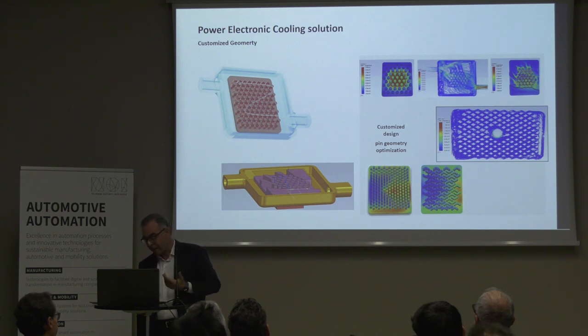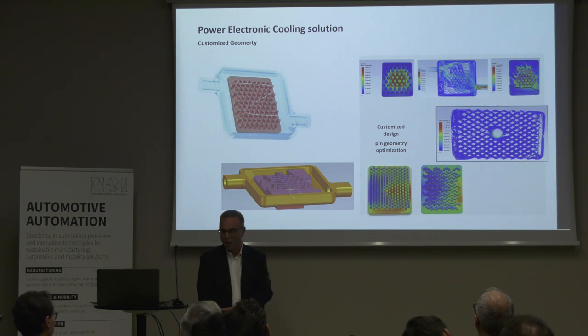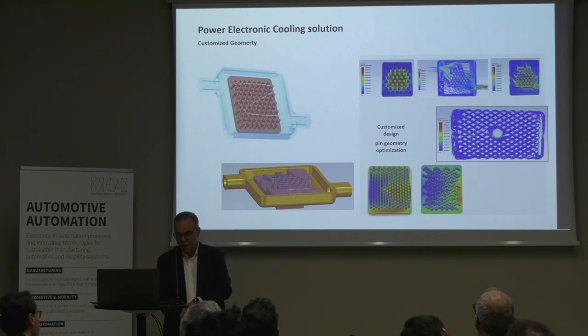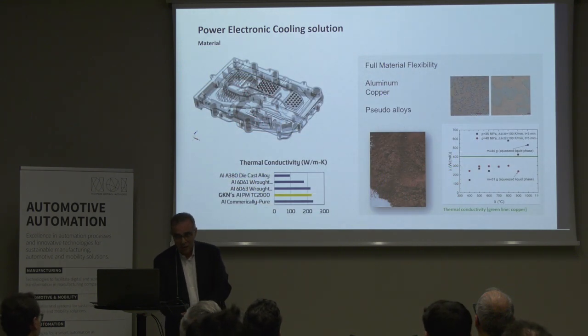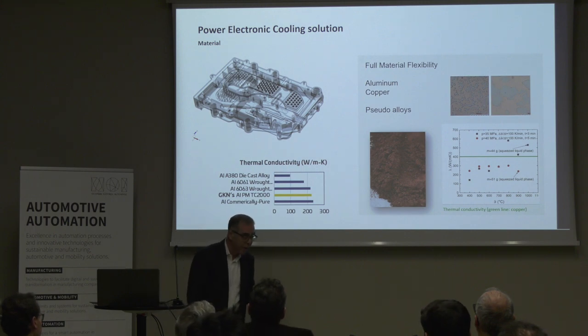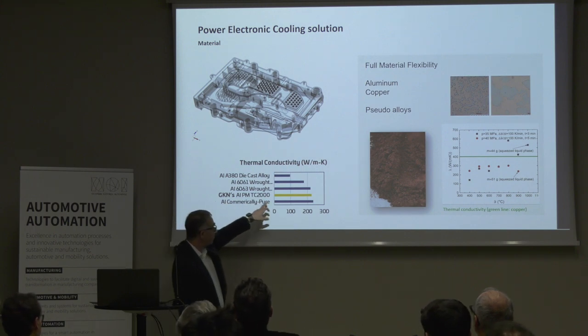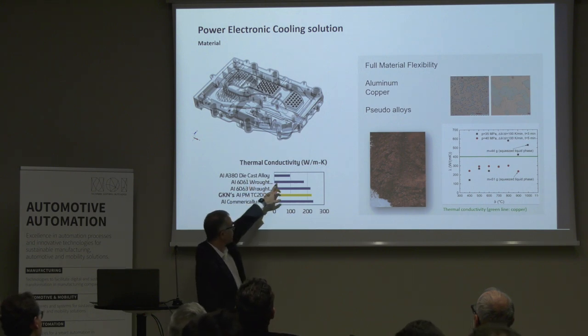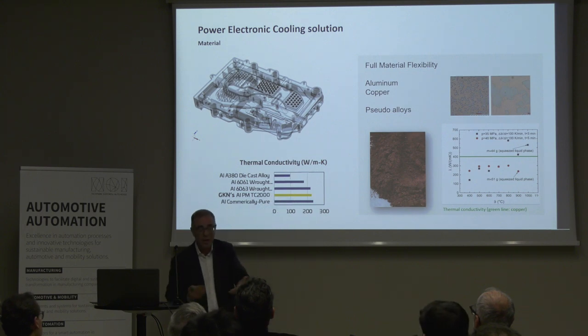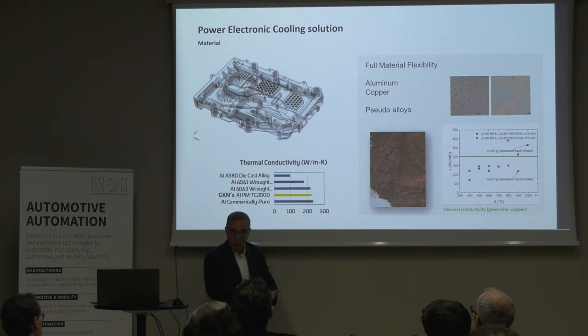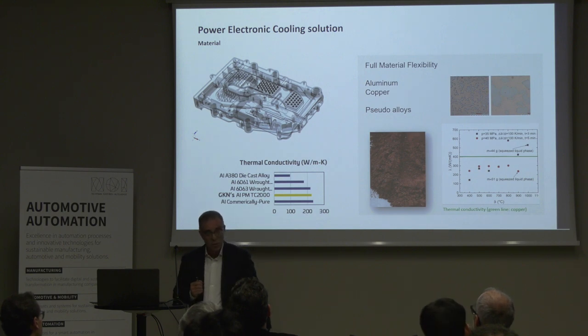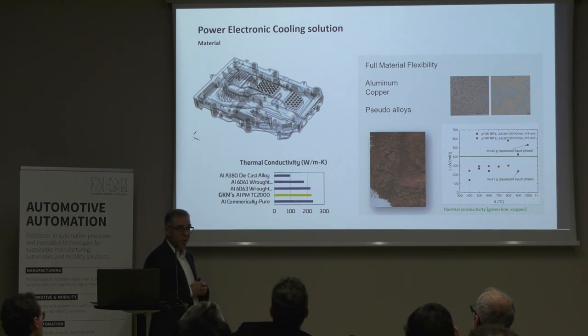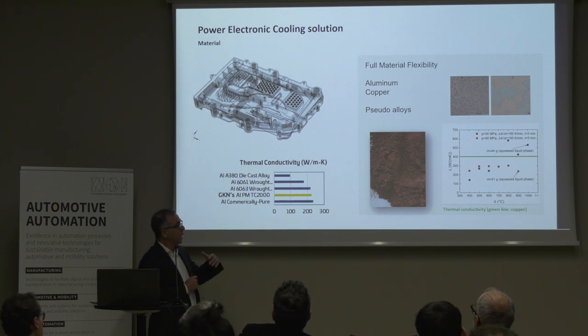The other great thing that our technology, powder metallurgy, can offer is material flexibility. We developed an aluminum alloy that is really far above the die-casted alloy. And that's mainly the reason we are using aluminum heat sinks coming from our technology, powder metallurgy, into the die casting. So that's one point of synergy that we also have with Alupress, actually.